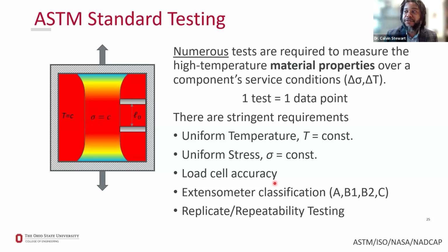Because of that, you have to develop very stringent requirements for every test that you run. And because of those requirements, you need to also run many, many repeat tests in order to qualify the uncertainty of your test methods. So specimens need to be subject to uniform temperatures with very tight tolerances of plus or minus 2 degrees Celsius. You need uniform stress, both in the design of your sample, but the alignment of your load chain. You need to calibrate your system to know the accuracy of your load cell, your thermocouples, your extensometers. And then you need to repeat your tests multiple times and get your standard deviation, your mean values. All of this then leads to you needing to do tens to hundreds of tests for any particular material of interest if you're subjecting it to extreme environments, ranges of stress and ranges of temperature.